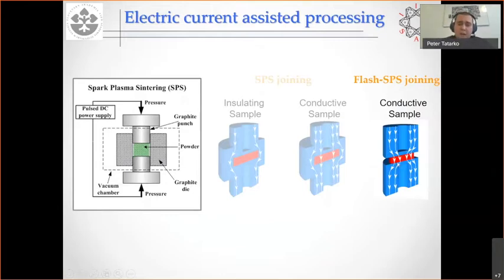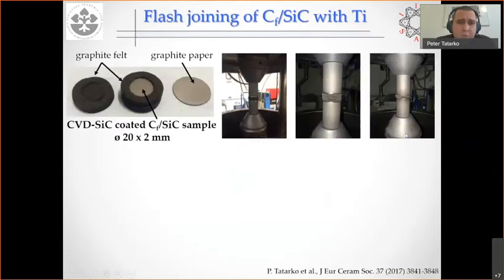So this is the second part of my talk, in which I would like to explain how we developed this. What we did was quite simple. We wrapped the sample in the graphite felt. You see here is our sample, CVD silicon carbide coated carbon fiber reinforced silicon carbide, and we wrapped it within the graphite felt. Then we put it in between two graphite punches in the SPS machine. Then we applied a little bit of pressure, and we applied the current.